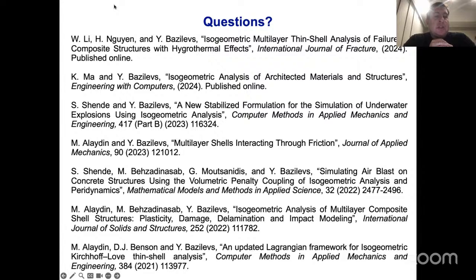The structure is still relatively thin in the thickness direction, even for the multi-layer case, relative to its overall size. And so we're probably not very accurate at tracking shocks through the thickness of the structure. However, it appears that we're able to capture delaminations and fractures very well. So if you want to see if you have any residual life left in your undersea vehicle, we should be able to do the calculations at least at the component level and predict how badly damaged the structure is. Tracking shockwave propagation through the thickness would require a much different approach to these problems.